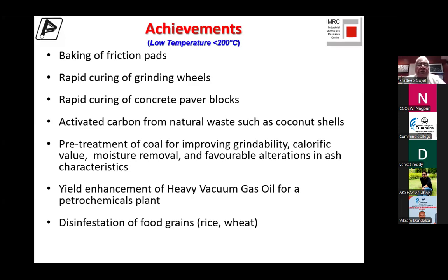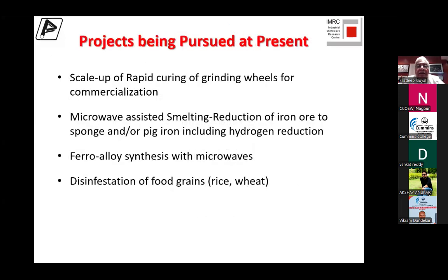So what are the low temperature processes that we did? Baking of friction pads, rapid curing of grinding wheels, rapid curing of concrete paver blocks, activated carbon from coconut shells, pre-treatment of coal for improving grindability, yield enhancement of heavy vacuum gas oil for petrochemical plant, and disinfestation of food grains. Now, suddenly you will find that we are moving from industrial processes to a food industry process. And it's a very interesting thing. I will come to that also as we go later. So it's just a summary of what we had done.